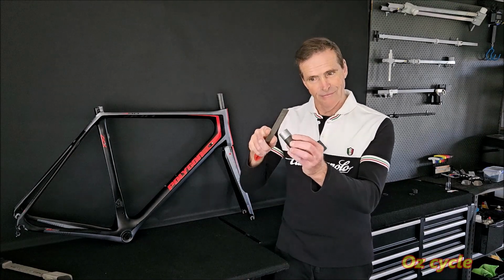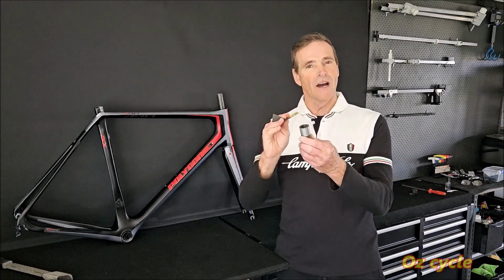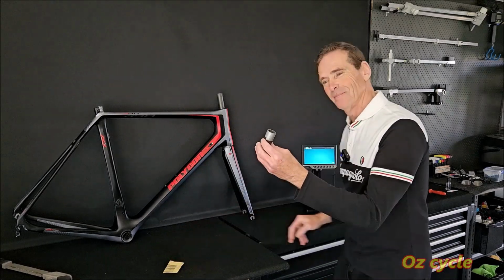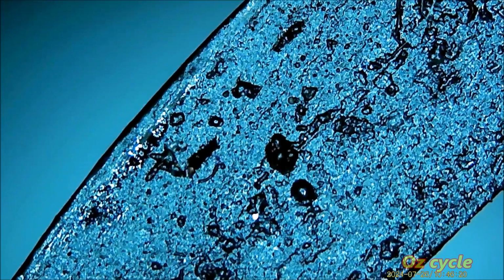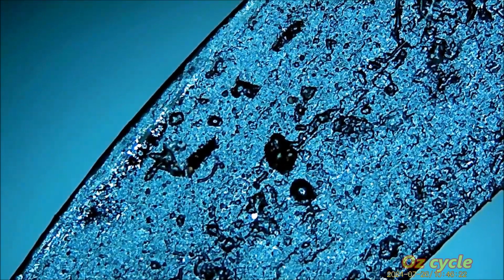Once we've filed it, that seemed to make a big difference. Now you can't see any big splinters sticking out, just very, very small ones. And also, once we've sanded it with the 400 and then the 1000 emery paper. Well, now the edges are very, very smooth. The facing edge also being smoothed off, now we can see air pockets and resin-rich patches. If you were to touch the surface with your skin, the splinters would be very, very small.